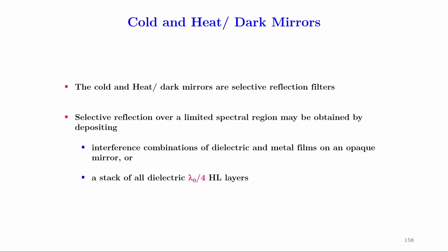The cold and heat or dark mirrors are an extension of the reflectance system that we have just seen. The cold and heat or dark mirrors are selective reflection filters. Selective reflection over a limited spectral region may be obtained by depositing interference combinations of dielectric and metal films on an opaque mirror or all dielectric lambda 0 by 4 high-low layers.